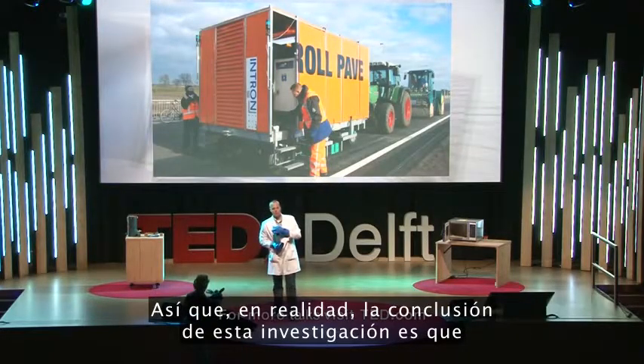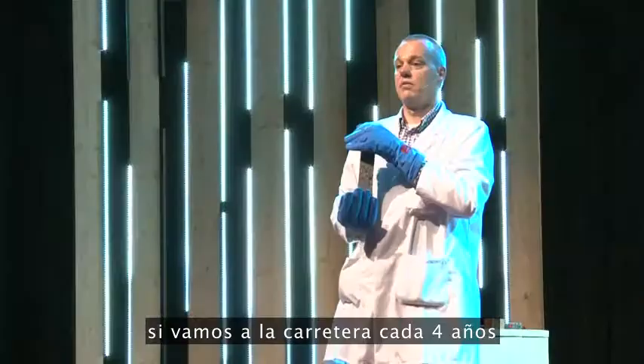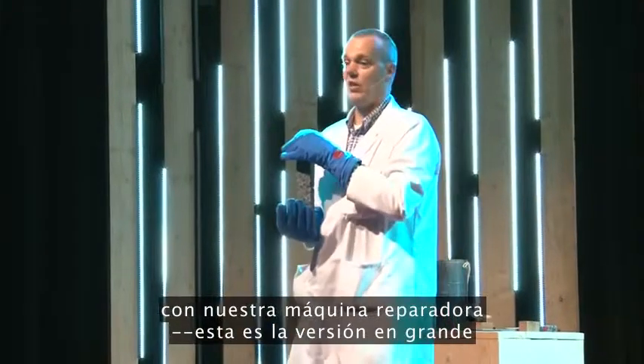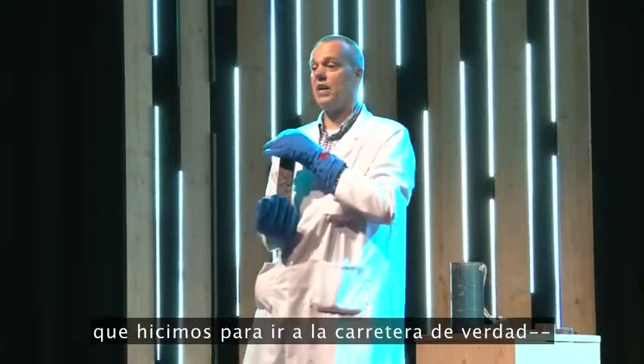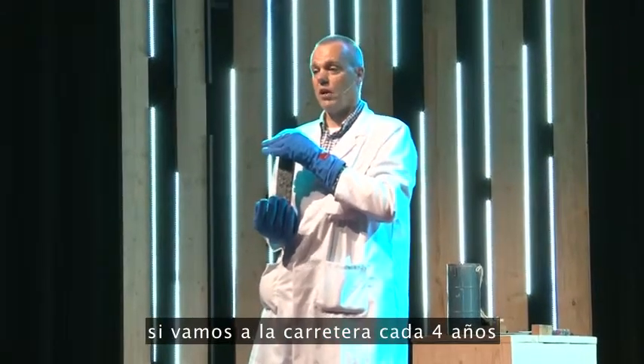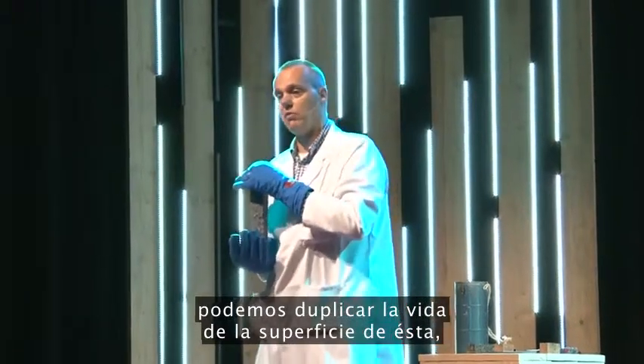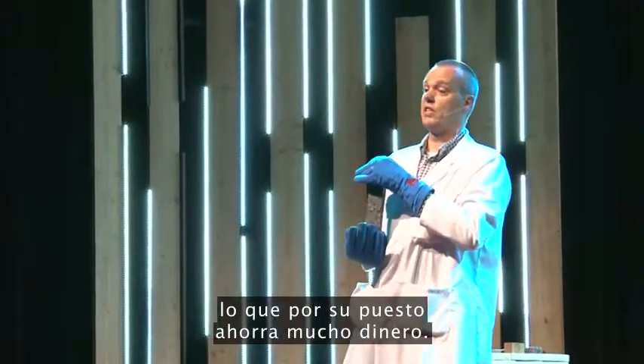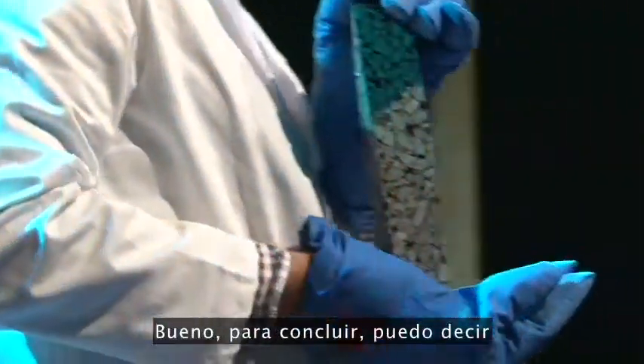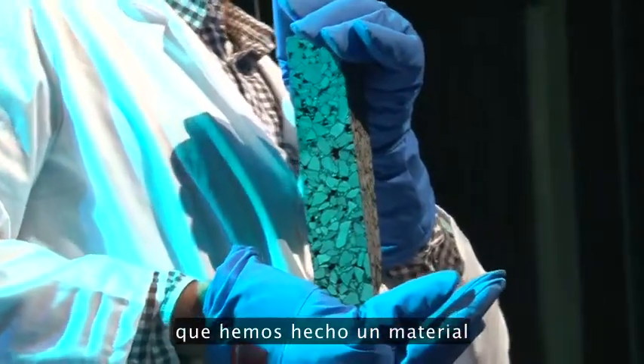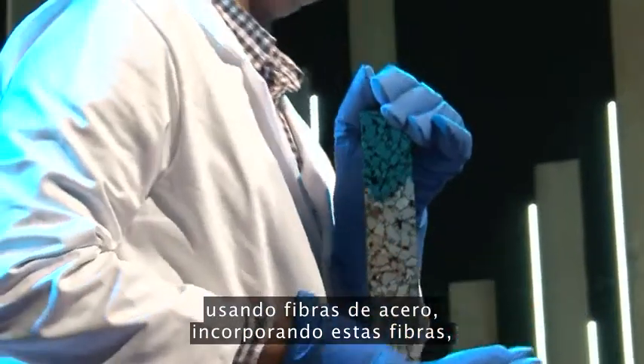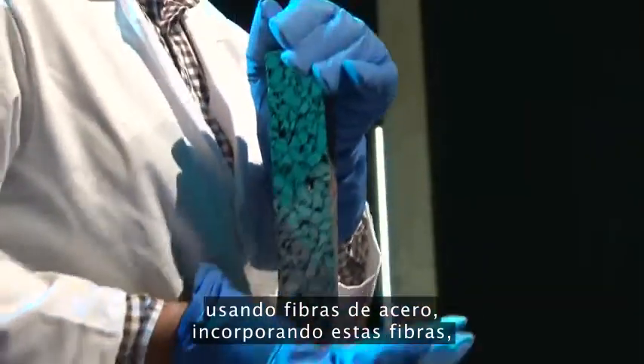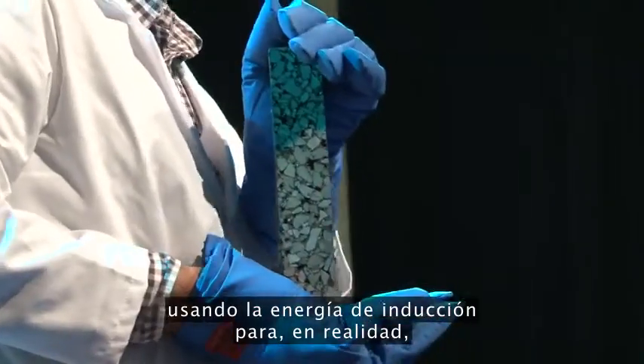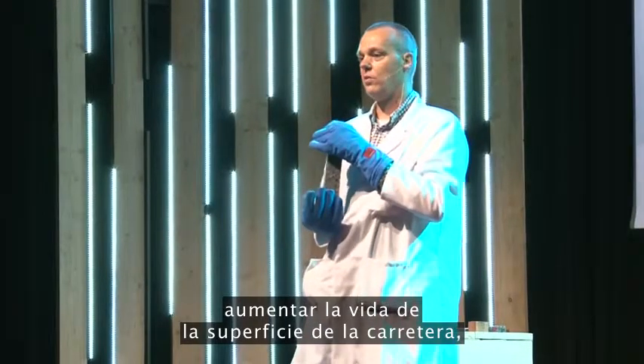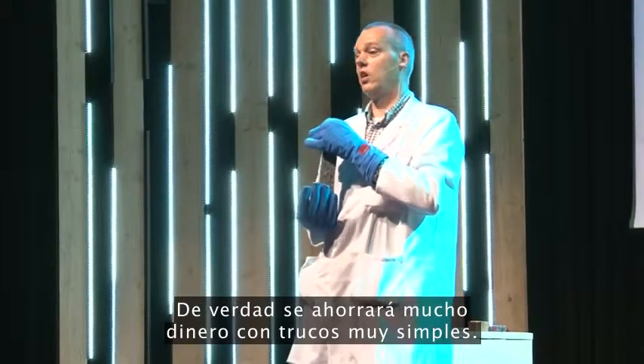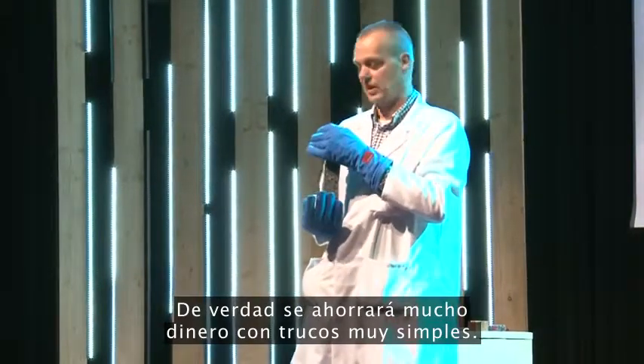So actually the conclusion from this research is that if we go on the road every 4 years with our healing machine, this is the big version we have made to go on the real road, we can double the service life of this road, which of course saves a lot of money. Well, to conclude, I can say that we made a material using steel fibers, using induction energy to really increase the service life of the road, double the service life you can even do, so it will really save a lot of money with very simple tricks.